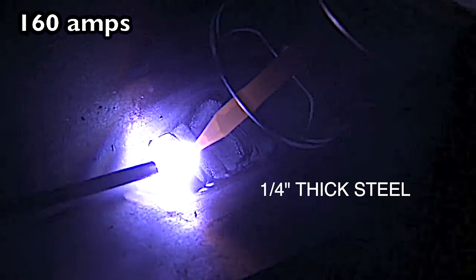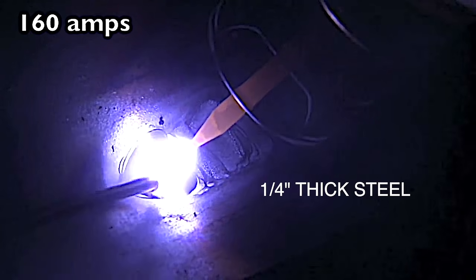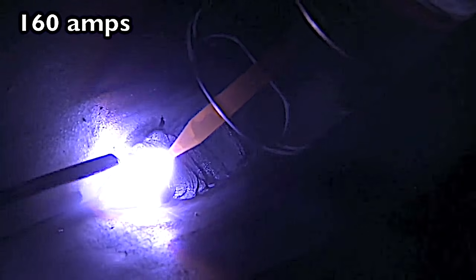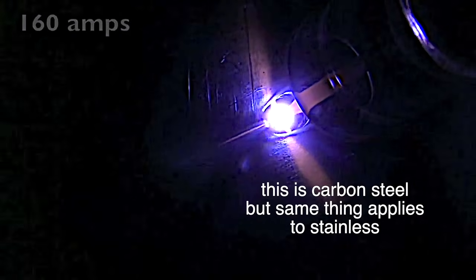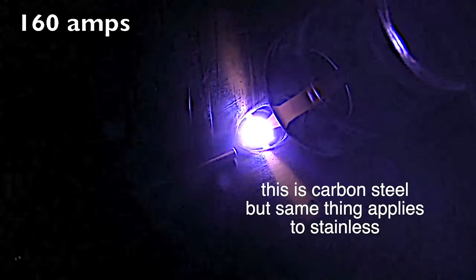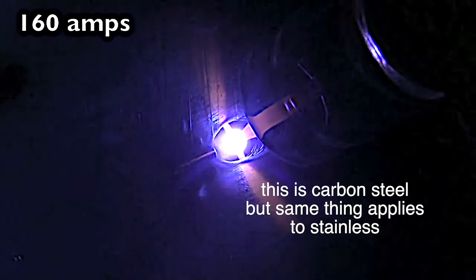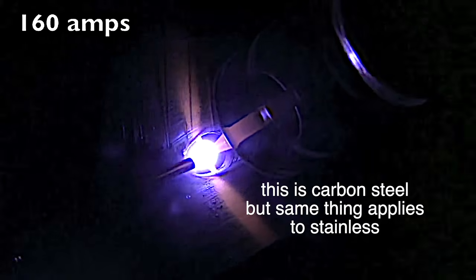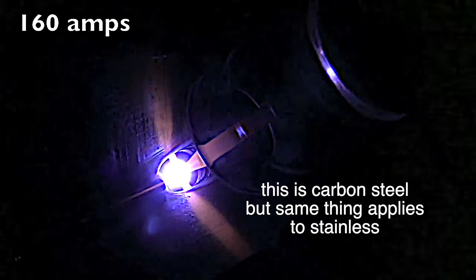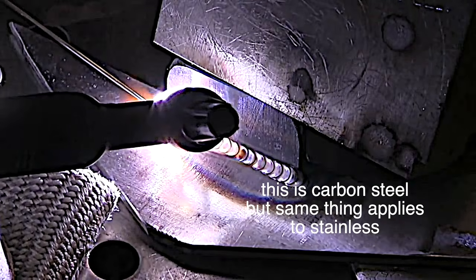Here's an instructive shot on what happens when you don't use a tight arc length. When you use a long arc, you're not taking advantage of the pinpointed heat of TIG welding, and things don't go right. Your rod blobs in there instead of feeds in there. All I did here, same amperage, same everything, was tighten that arc length up, and you can see the tremendous difference. Everything gets more controllable, more precision.